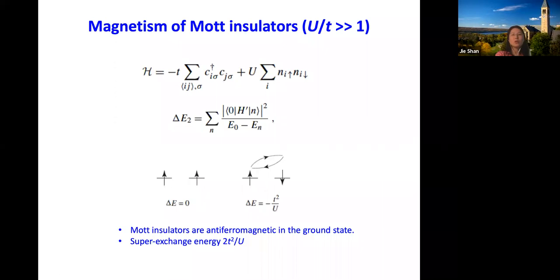The other thing we also know pretty well is the magnetism of Mott insulators in the limit of a large U over T. So in this limit, you can think of this Hamiltonian as unperturbed, and this T is a small perturbation. To figure out whether parallel spin or anti-parallel spin gives you a lower energy, you can think of this super exchange process. It's like this: an electron hops over and hops back. So this is described by second order perturbation theory.